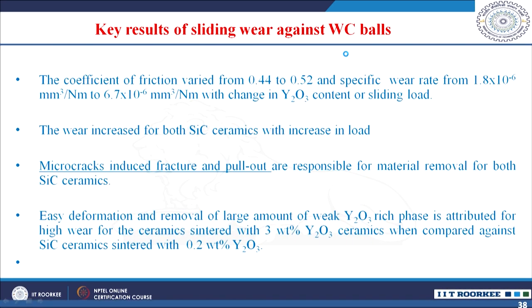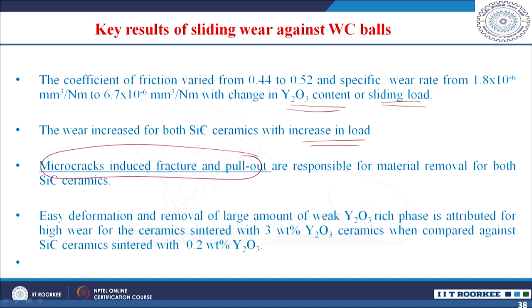Key results from sliding wear against tungsten carbide balls: coefficient of friction varied from 0.44 to 0.52, and wear rate from 1.8×10⁻⁶ to 6.7×10⁻⁶ mm³/N·m with change in yttrium oxide content or sliding load. Wear increased for both ceramics with increasing load due to increased fracture. Microcrack-induced fracture and grain pullout are responsible for material removal. Easy deformation and removal of the weaker yttrium oxide-rich phase is attributed to higher wear in ceramics sintered with 3% yttrium oxide compared to those with smaller amounts of additive.